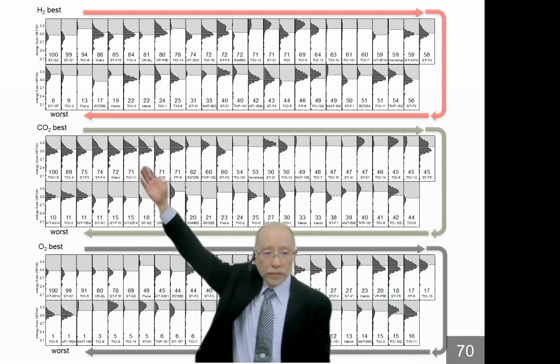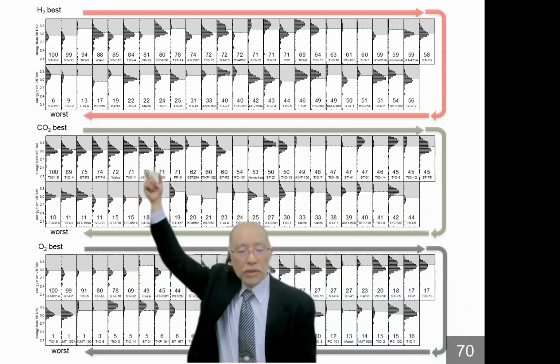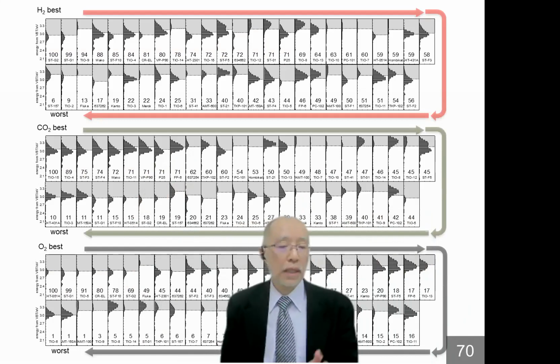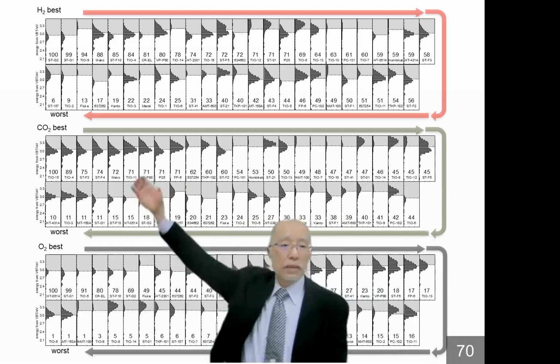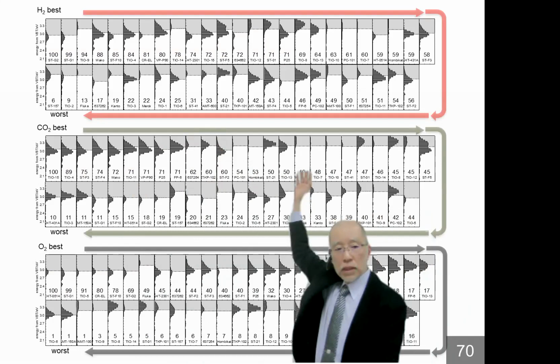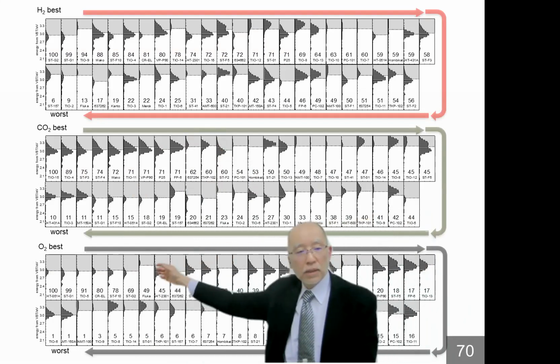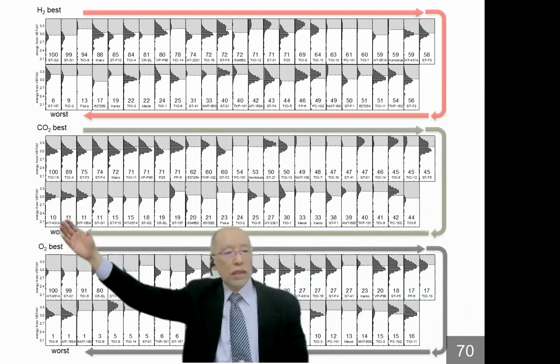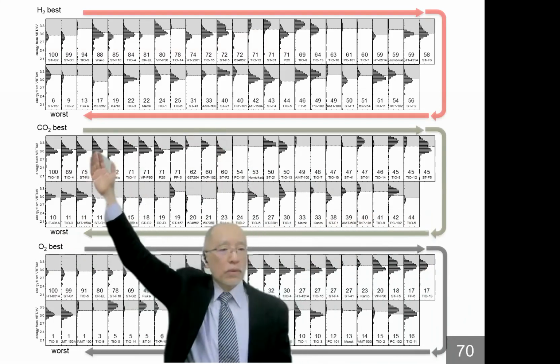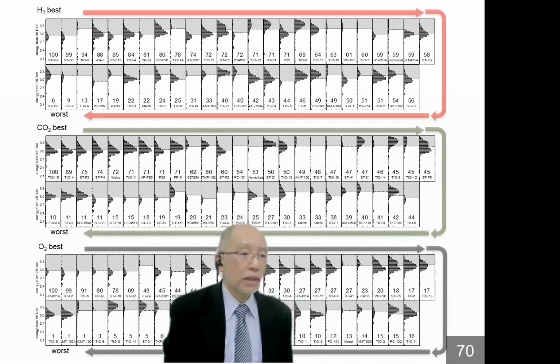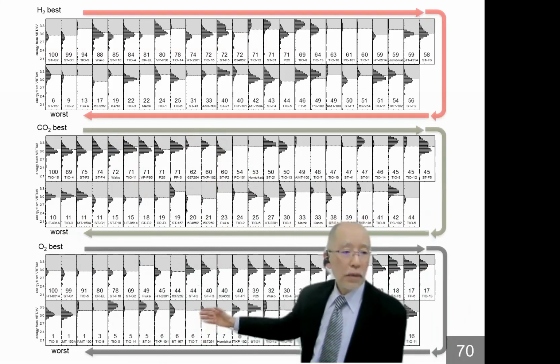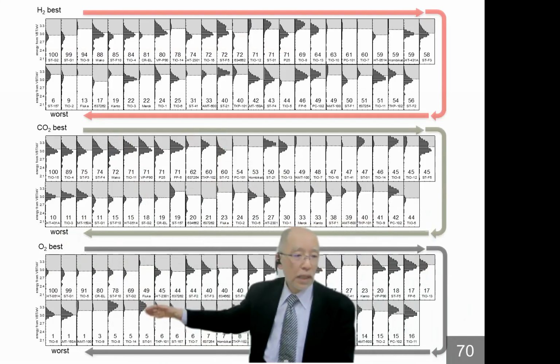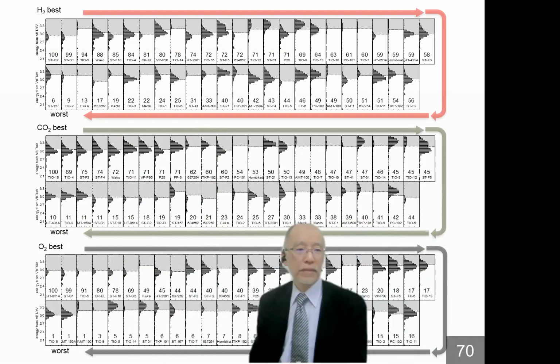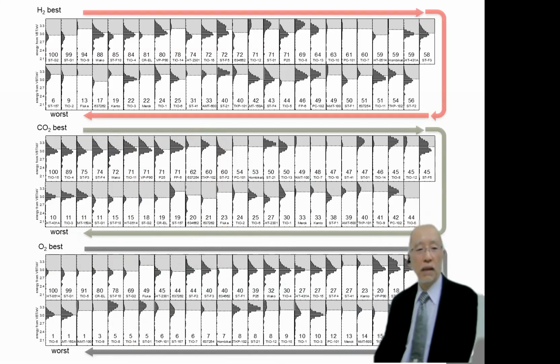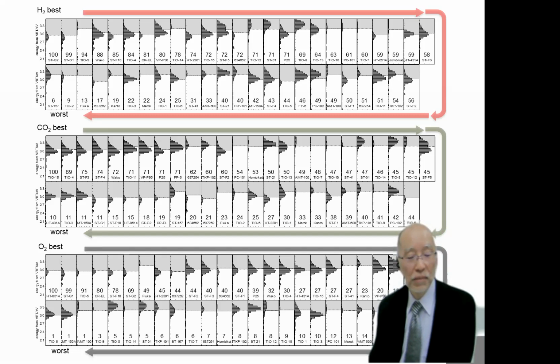The left top is the highest, with relative activity 100. And this is decreasing, decreasing, and the left bottom is the worst. For hydrogen evolution, the worst one has a relative activity of 6. For carbon dioxide, that is 10, and for oxygen, that is 1. And there is almost no relation, not so good patterns.